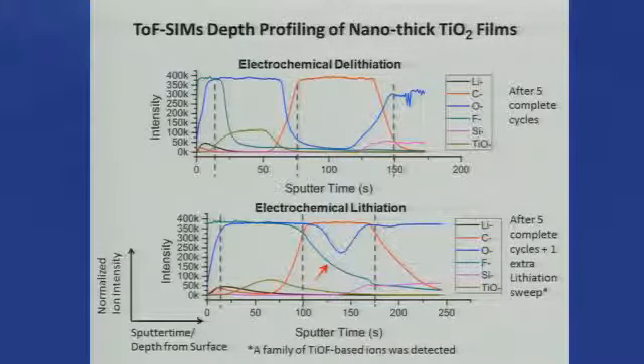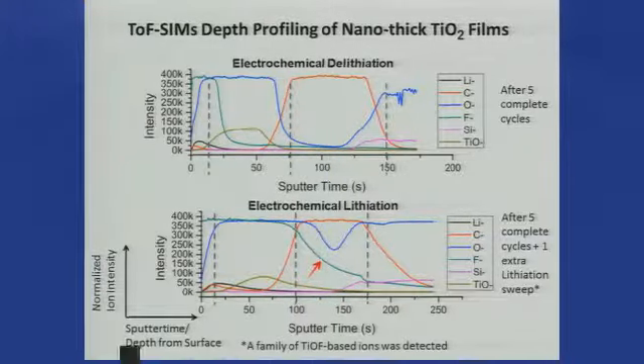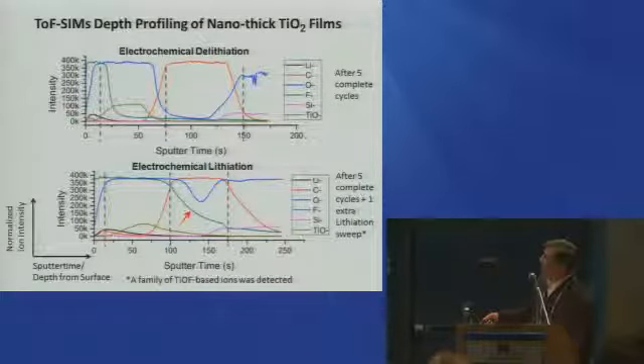And then we've fabricated this on quartz. And so this is the other interface here. So we get very precise alignment with these different interfaces. Because it's so flat, we get very good depth profiling for these particular materials. And we can actually look at where the oxygen is in the titanium film that's co-localized with TiO2. The signal is not quite as big, so they're normalized mainly to this peak here. And then where the lithium is, it's primarily trapped at the interface.